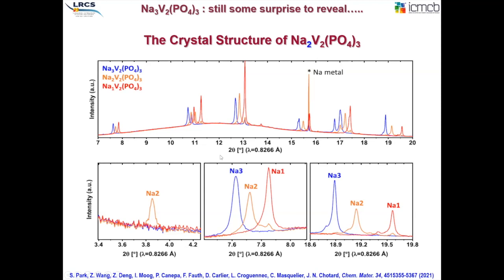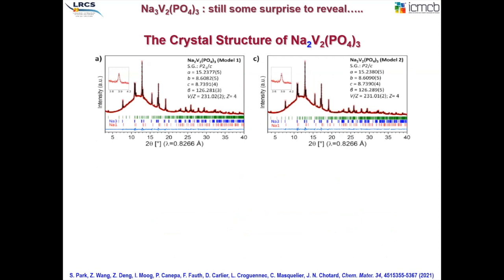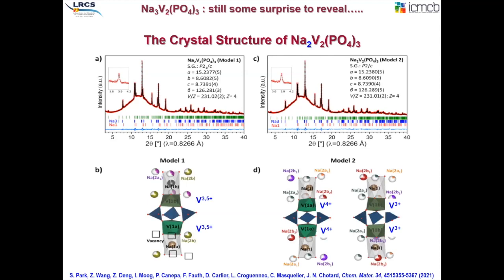oxidized one. From the very high quality of this synchrotron X-ray diffraction pattern, we were able to determine the crystal structure of this new Na2V2(PO4)3 phase. It was a little bit challenging, and my colleague Jean-Noël Chotard with Sung-Kyu Park, our student, and our collaborators worked very hard trying to figure out the real crystal structure. We ended up with two models that we couldn't really decide between: one showing sodium vacancies in one crystallographic site, and the other showing full disorder of sodium on the crystallographic sites, while the two specific lantern units of the NASICON framework are oxidized to vanadium 4+ on one side and to vanadium 3+ on the other side.